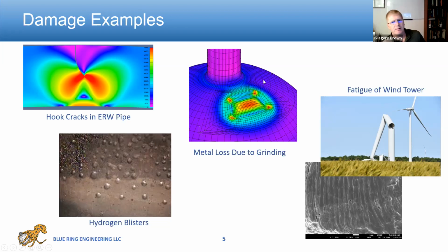In the middle, you see metal loss. This is external metal loss. This is actually not corrosion. This is actually metal loss due to a repair where they ground out cracks. We want to know if we still have enough wall thickness to safely hold that pressure. So this is a computer model to determine if that equipment is still safe to operate.